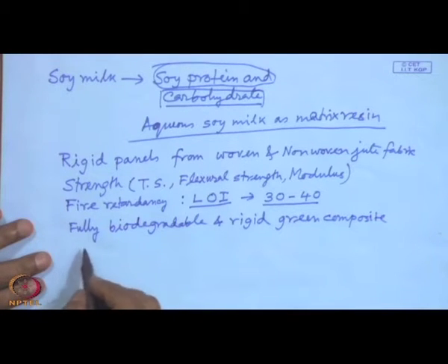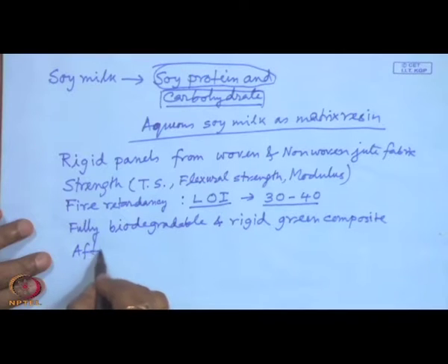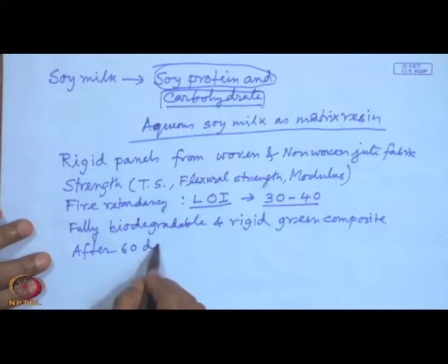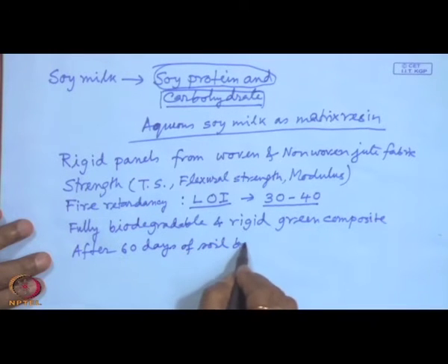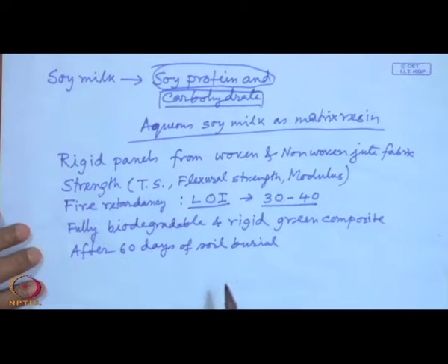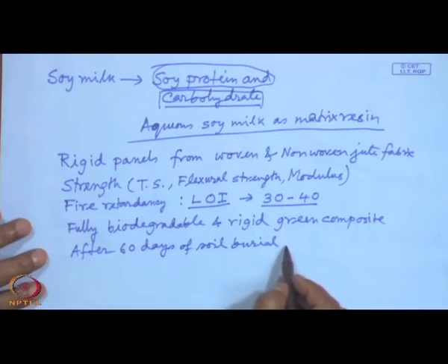We have measured the biodegradation, evaluated the biodegradation characteristics of these composites. We have found that after 60 days of soil burial, in compost condition, the composites become brittle and fragmented.